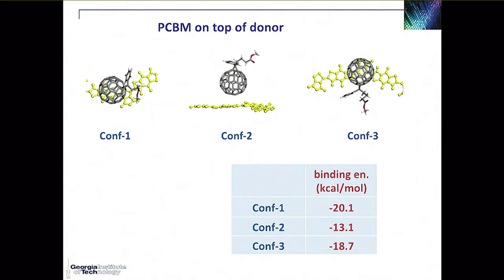And then you can see pretty large differences in binding energies. In the case of that configuration, the binding energy jumps up by about 50% to reach some 20 kilocalories per mole. In the case of the second configuration, with the side chain being away, of course, that's the same thing as if there had been no side chains on the fullerene. The binding energy is the same as in the case before, 13 kilocalories per mole.